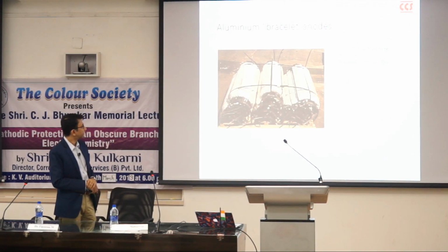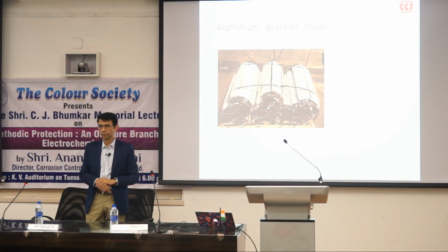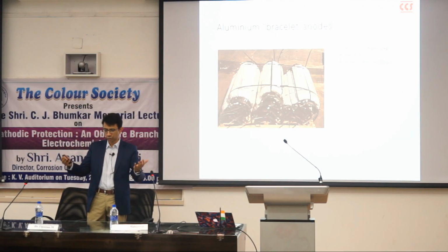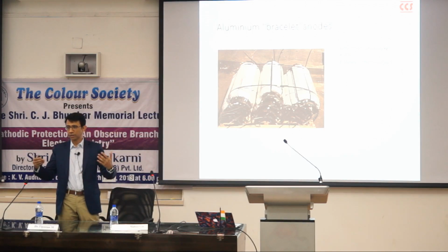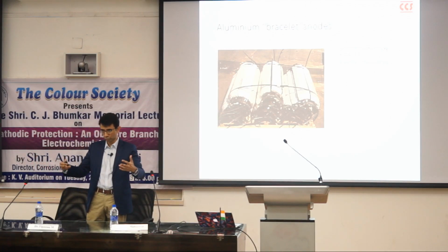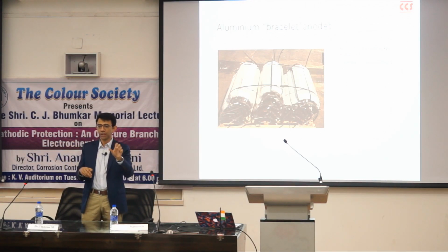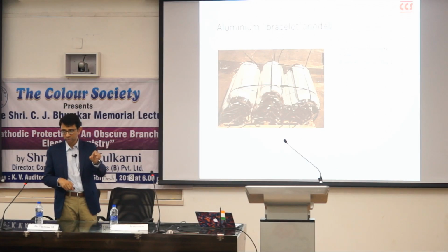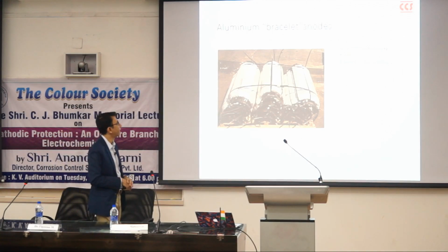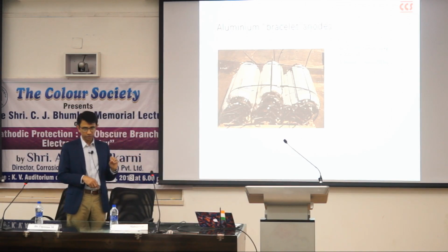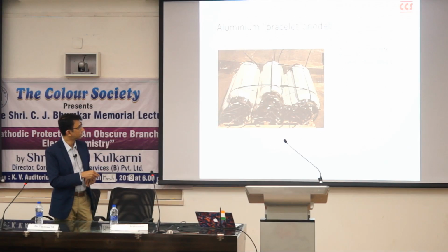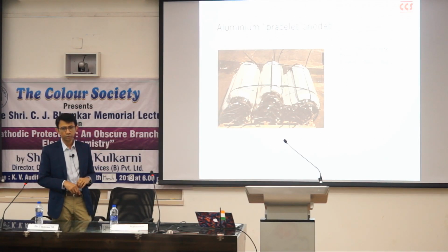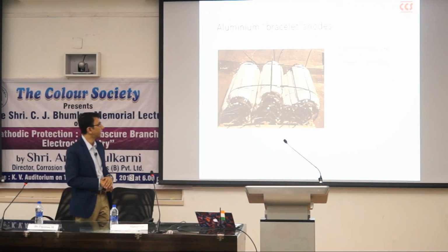This is an aluminium bracelet anode, and as the word suggests, it is used for subsea pipelines. So, when you have a subsea pipeline which is going to be laid on the bed, it is typically not only coated with some kind of protective corrosion barrier coating, but it also has a cement coating, and parts of the pipeline are left uncoated with cement so that this anode, aluminium anode, can be fitted on it. Aluminium is the most efficient anode for marine applications simply because its rate of consumption is very low. Zinc, if you remember, was 11.1 kilograms. This is only 3.1. It's a no-brainer. So, aluminium is far more actively used than zinc for marine applications.